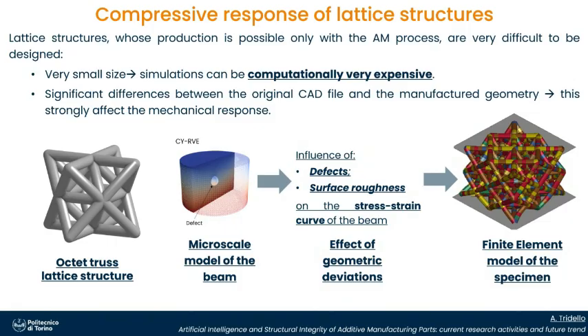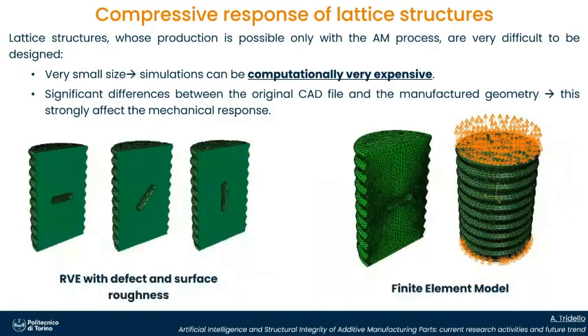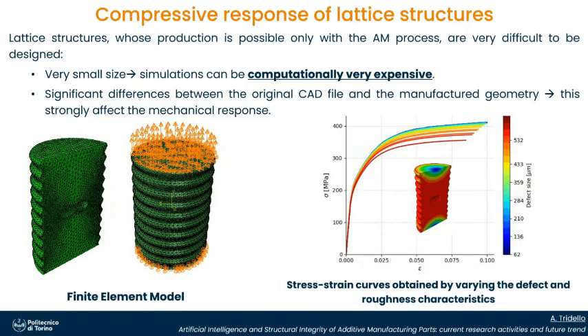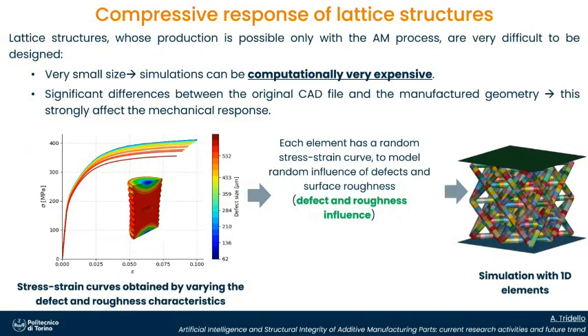So this is the finite element model of the specimen. Here you can see the RVE with the defects. We take into account also the orientation of the defect. And here you can see the different stress strain curves due to the presence of the defect and a specific roughness. Then each element has been assigned a random stress strain curve, which derives from a specific roughness and a defect.